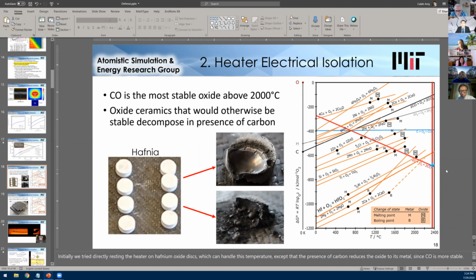Okay. So this diagram is just showing oxides. And so what the result of this Ellingham diagram says is we can't use any oxides in the hot zone. Can't use oxide insulation, either thermal or electrical. But if I had an Ellingham diagram for carbides, the reason I'm suggesting tin as an alternative material is because it doesn't form a carbide. And so if you have carbon and tin as your only elements in the system, there's no reaction that forms between them, and the solubility is just far lower, which is mainly because a carbide doesn't form. If a carbide formed and then dissociated at, say, 2800 Celsius, like silicon carbide, that would increase the solubility.